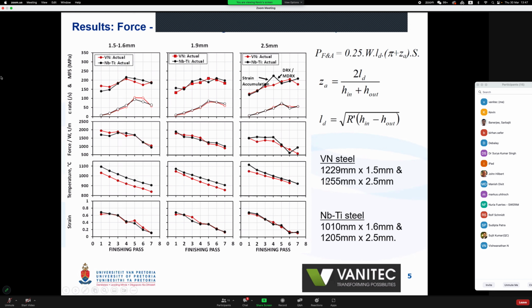Here we have 1220, 1250 millimeter wide material, as opposed to the niobium titanium steel on the ultra thin, in other words below 2 millimeters, where we were only comfortable up to 1,000 millimeters wide. So that was a major plus.